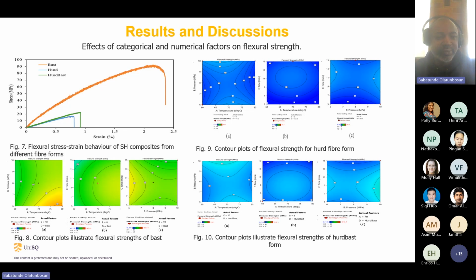Figure 8 talks about the 2D, or what we call the contour plot, that shows the flexural strength of bast using a combination of the factors of temperature, pressure, and time. Figure 8 talks about the bast, while figure 9 gives us the contour plot for the hurd, and figure 10 is about the hybrid, which I call the hurd-bast. Generally, later in my slide, I'm going to show you how those parameters have a way of affecting these properties. These are images from the SEM, which will be shown later.